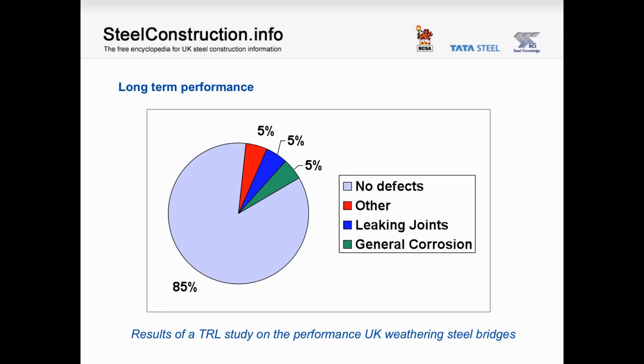Weathering steel also has a good track record in the UK. TRL carried out a study in the late 90s, early 2000s on the performance of all UK weathering steel bridges. What they found was that it's generally performing very well, with 85% no defects. Where they did find problems, it was specific faults on a few occasions, typically leaking expansion joints. However, if you notice on the slide the green area, 5% of cases were due to general corrosion, and this was almost always due to the use of weathering steel in the wrong environment.